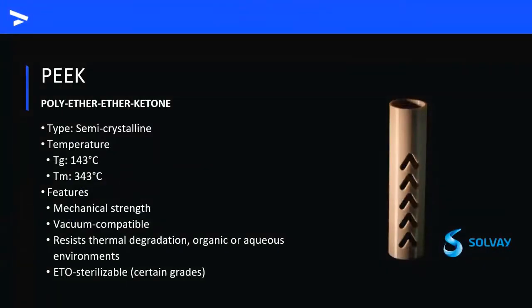Let's move on to talking about our three high-performance materials, PEEK, PEKK, and ULTEM. PEEK is a high-performance semicrystalline thermoplastic in the polyaryl ether ketone family with a glass transition of 143 Celsius and a melting point of 343 Celsius degrees. It offers excellent mechanical and chemical resistance properties that are typically retained up to 240 Celsius degrees, although some grades have continuous operating temperatures up to 260.